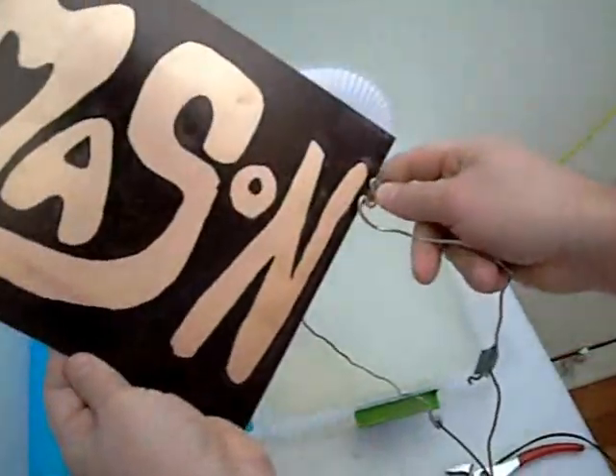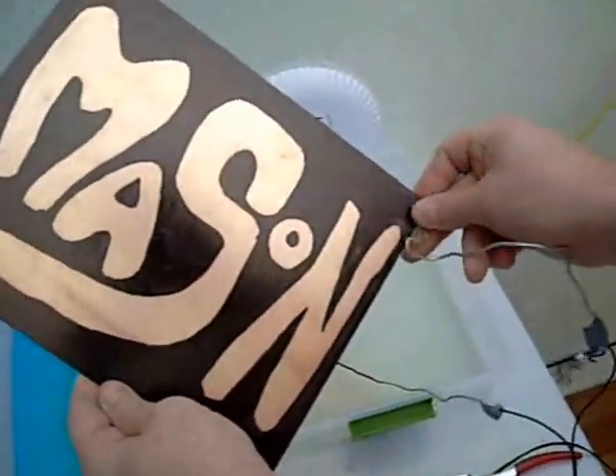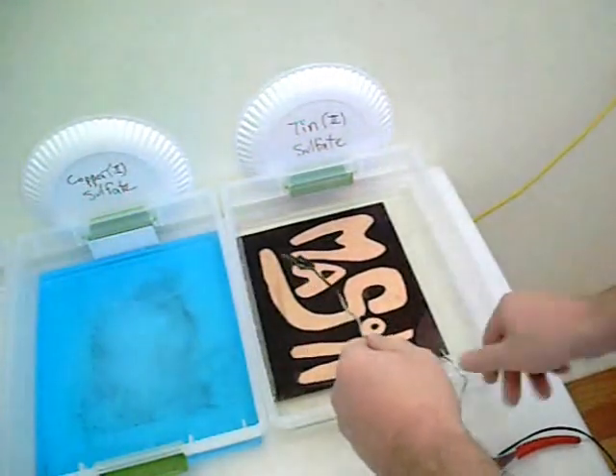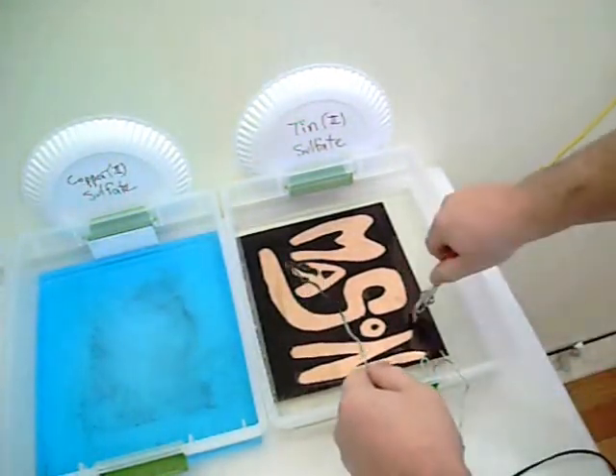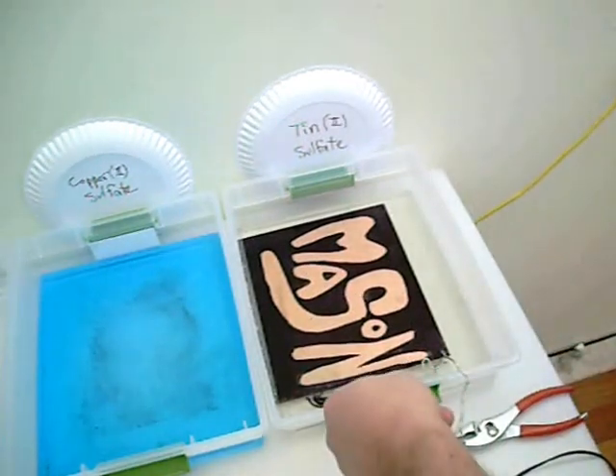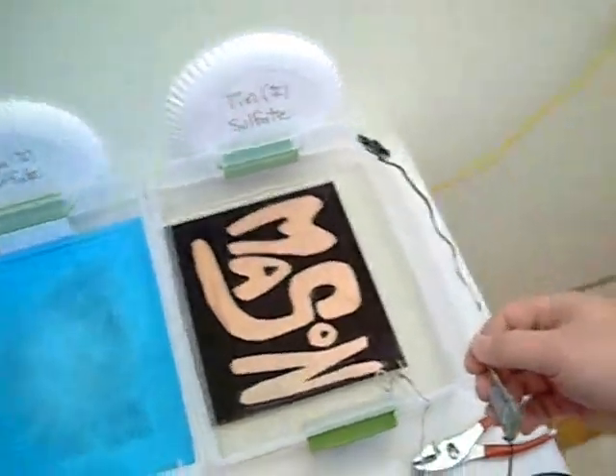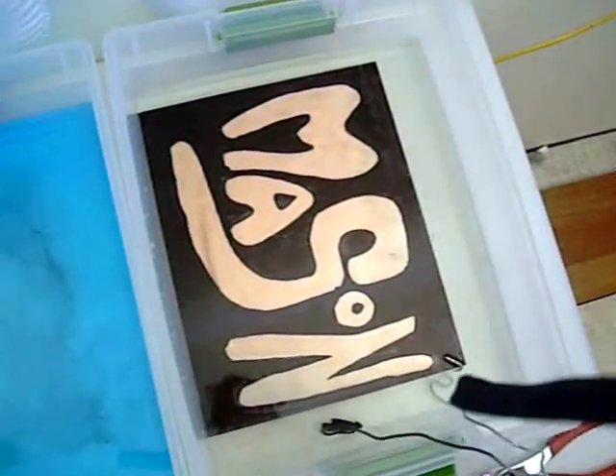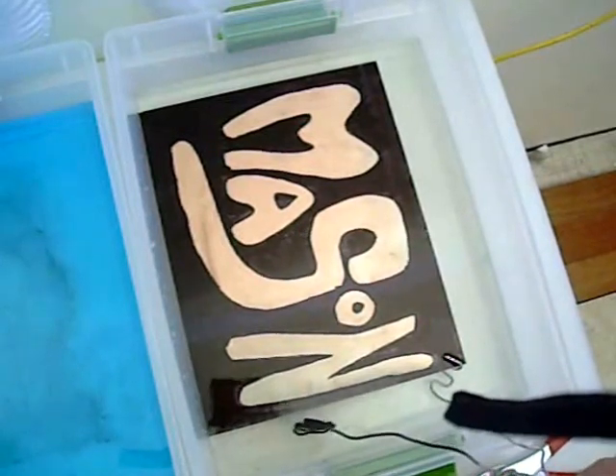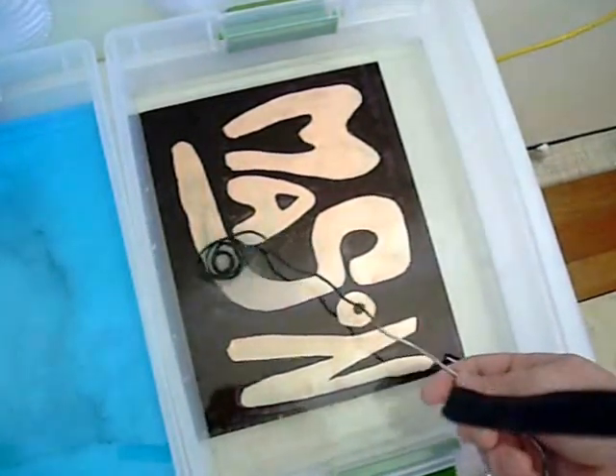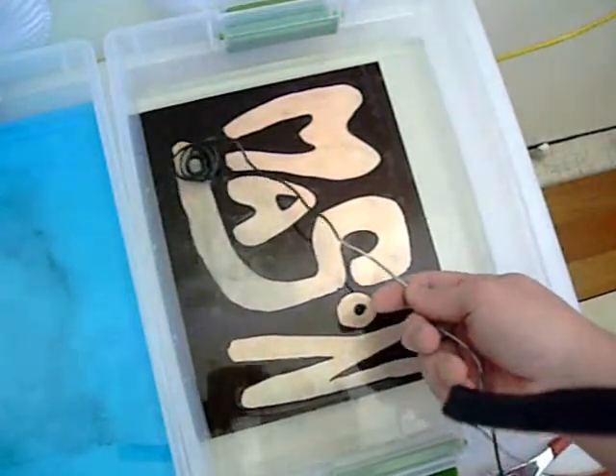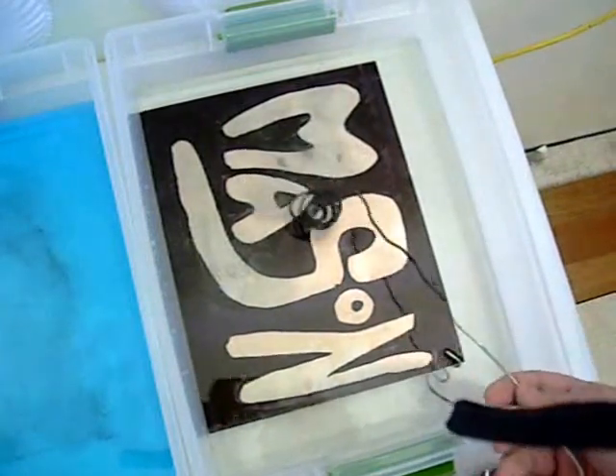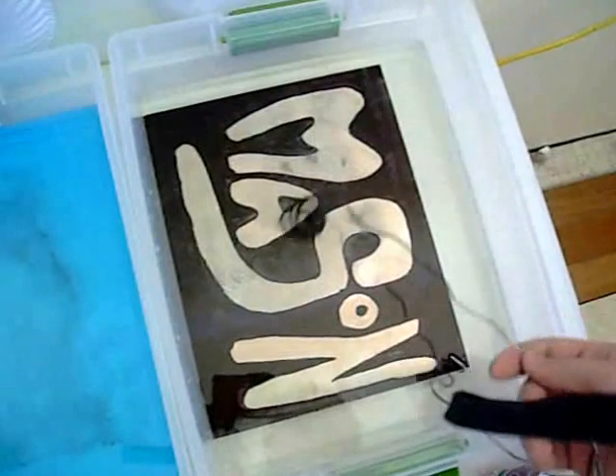Now this first nameplate, all that black is just permanent marker. That's going to act as a resist to resist the plating. So I've colored over with permanent marker the copper that I don't want to be coated in tin. You can see immediately when I dip the cathode into the water, the tin immediately starts to adhere to the area near the cathode. And I use that cathode as a paint brush almost, just barely touching the surface, being careful not to actually touch the plate. If you touch the plate of course you create a short circuit, and you'll make burn marks on your plate.